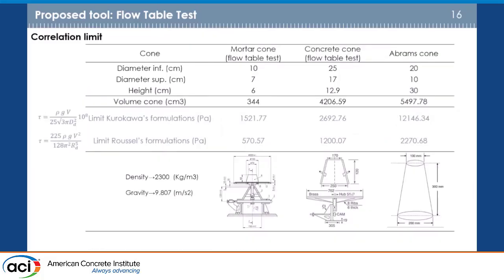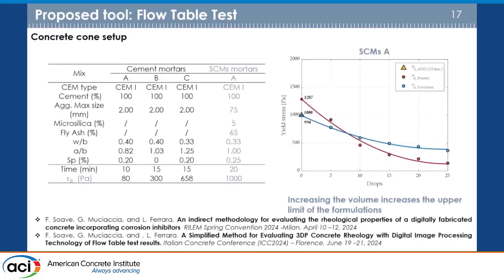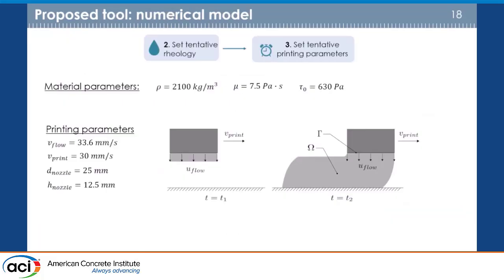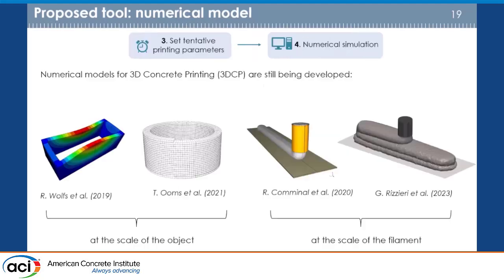The limits also depend on the volume of the material that you test, because we tried to apply the tests and the formulation not with the truncated cone for the mortars, but with the large slump cone for the concrete, and we found out that it actually depends on this. So we ended up with a medium size that we had in our lab, and it yielded reasonably good results in the correlations. We used these rheological inputs to feed a numerical model based on continuum fluid mechanics that we have developed in our lab in order to simulate the 3D printing process.